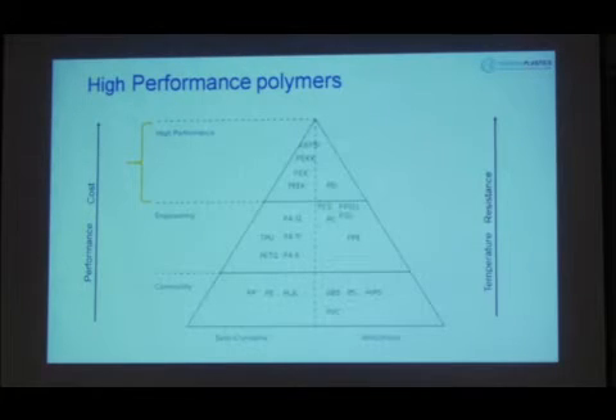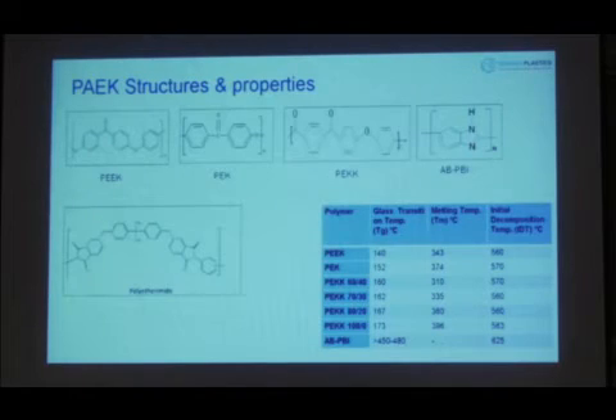In top floor, ABPBI is not yet visible in the 3D printing market. We are assuming and we hope that this material will come, because this material has the highest heat resistance. It can withstand up to 500 degrees C continuous temperature, and this is the only thermoplastic. Here you can see PAEK family members of the polymer, especially PEEK, polyether ether ketone, PEK, PEKK, and ABPBI.